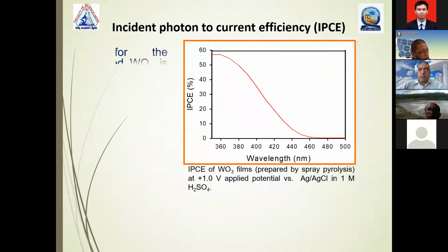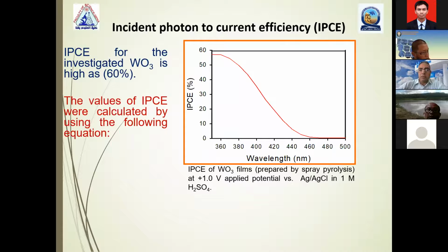The other experiments we can do to investigate the photoactivity of any material, whether it's a new one, as we try to find new electrodes for solar cells, or to improve the efficiency of known ones. We can measure the incident photon to current efficiency, which is called IPCE. For example, if we hit the electrode with 100 photons and produce 50 electrons, in this case we can say the efficiency is 50%. So the incident photon to current efficiency is measured against the wavelength of the light. It was found to be about 60% for tungsten oxide, and it can be calculated through the next equation in the slide, Brother Adi.